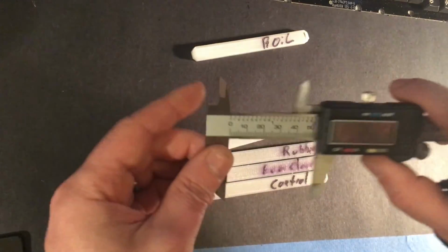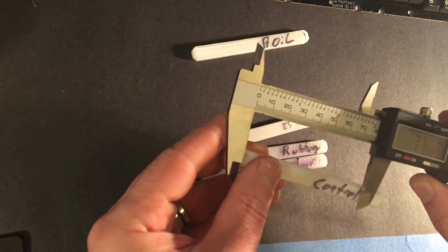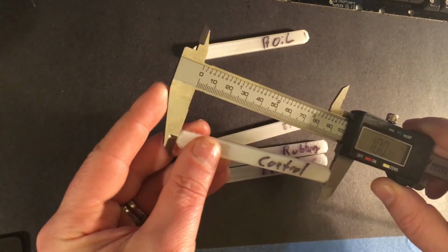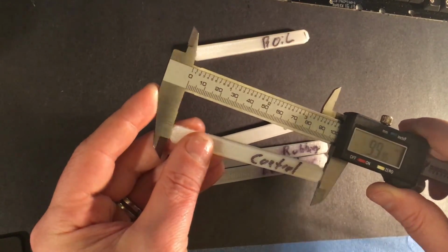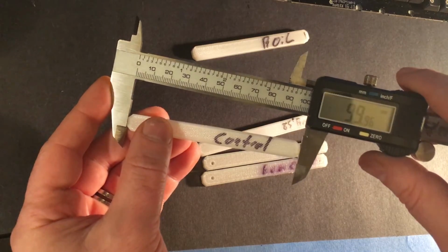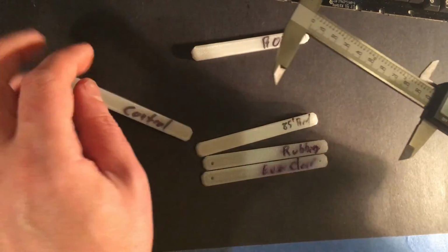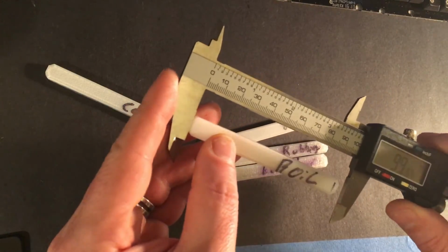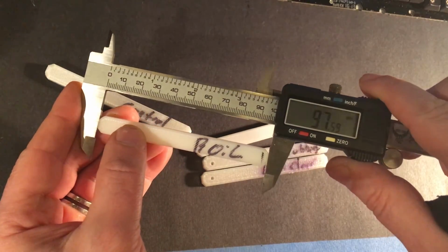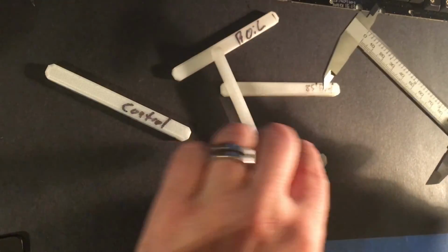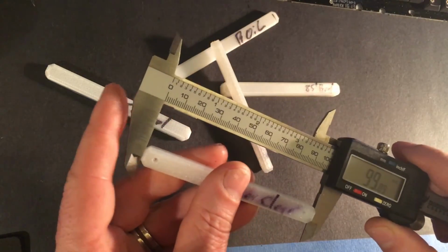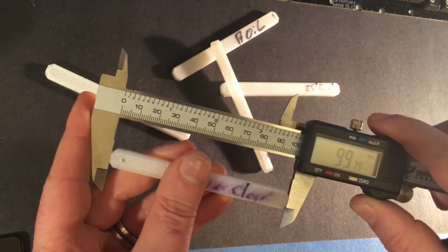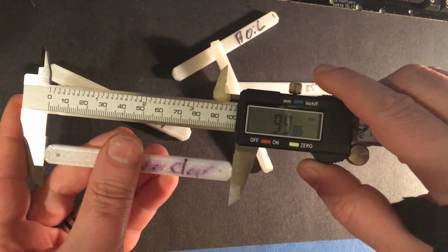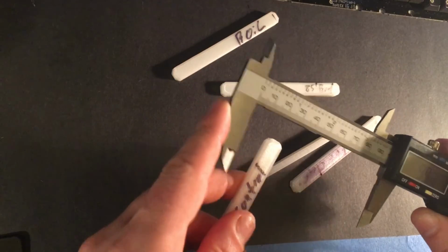So, on to kind of the point of this, dimensional stability along with the temperature deflection. If we measure the control that was printed on the slicer at 100 millimeters, you can see it's right around 100 millimeters, 0.04 off. Now, if we take a look at the boiled part, well, that's a lot smaller. We lost several millimeters there, a couple percent shrinkage. But if we look at the Everclear treated rod, it's almost exactly where it was with the other, within margin of error.